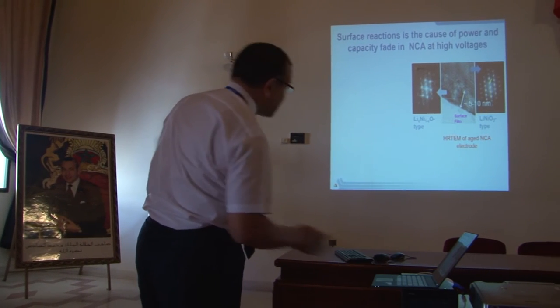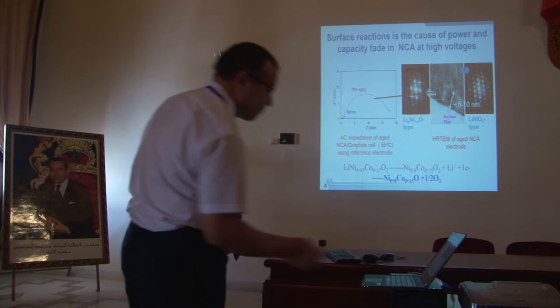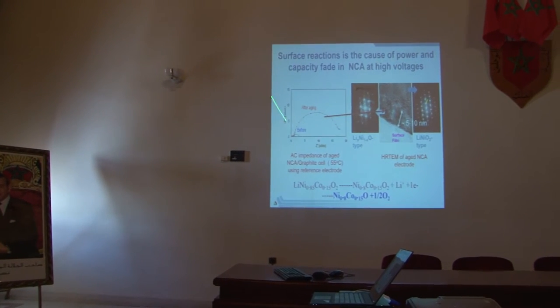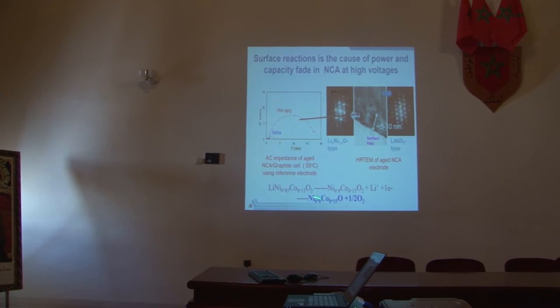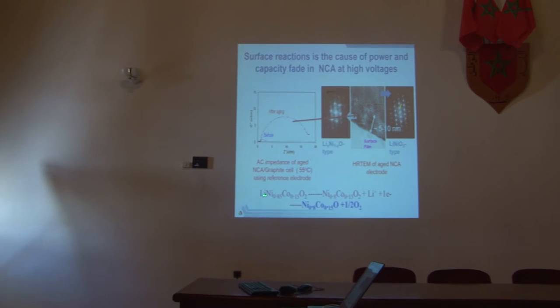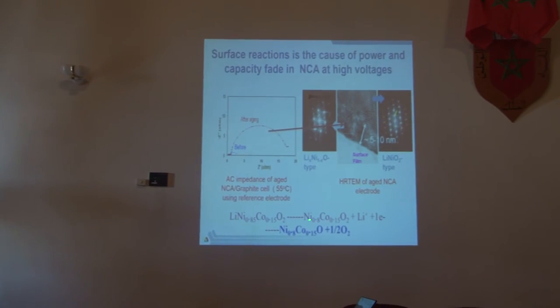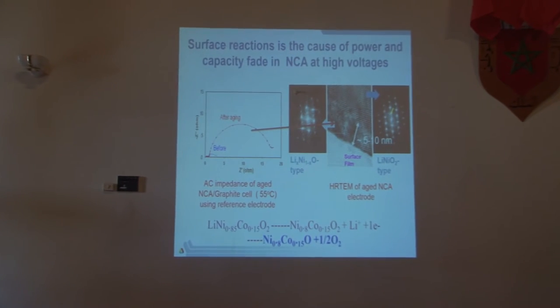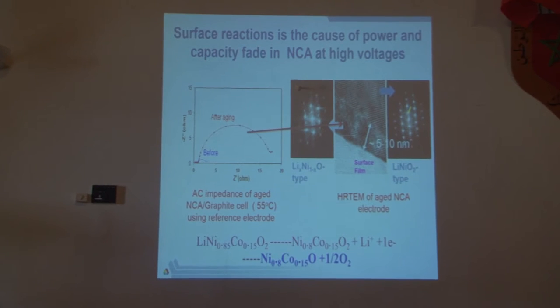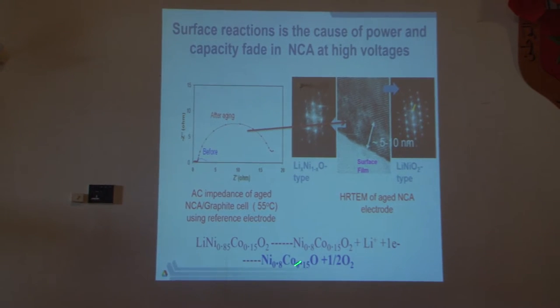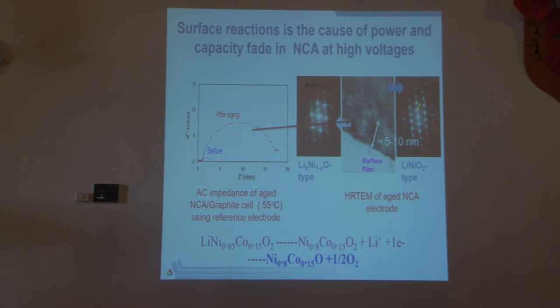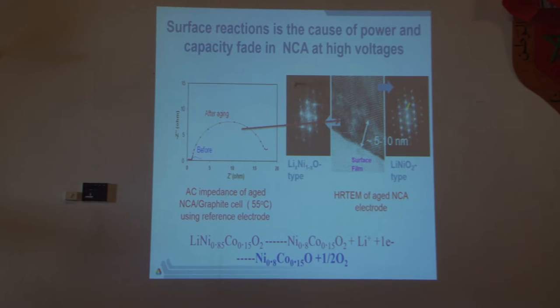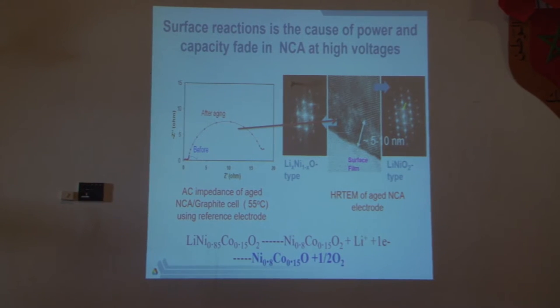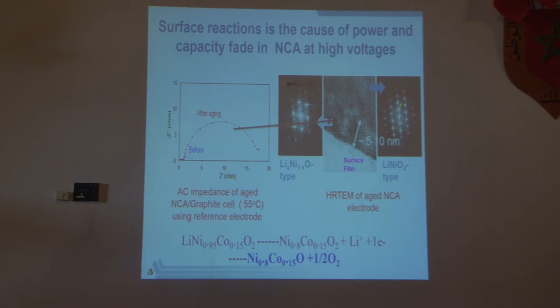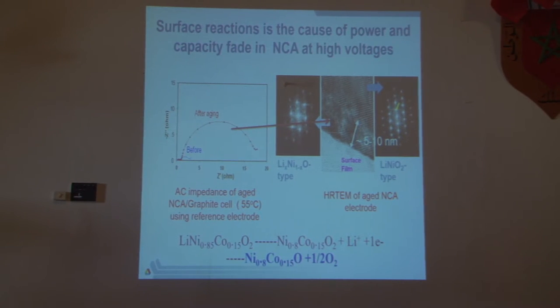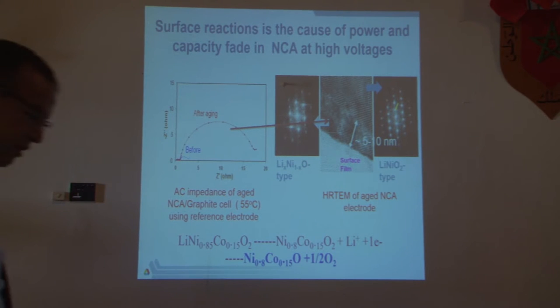And the nickel oxide phase is basically very insulating to lithium, and that's the reason why you get very high interfacial impedance. What happens is, when you charge, when you remove lithium from NCA, or nickel cobalt aluminum oxide in this case, nickel oxide or nickel cobalt oxide is thermodynamically unstable. NiO2 does not exist. You have an immediate reduction and release of oxygen, so you end up with this phase here, and the oxygen reacts with the electrolyte and gives you another film. Therefore, the interfacial impedance, where lithium moves through that interface, becomes much more difficult. And so having nickel-rich is attractive because it gives us high energy, but it is problematic because it reacts, especially when you go to higher oxidation states.